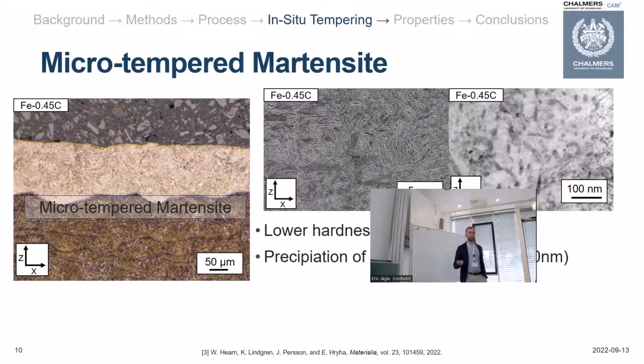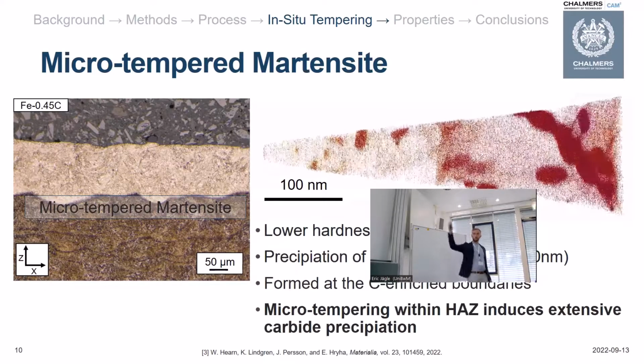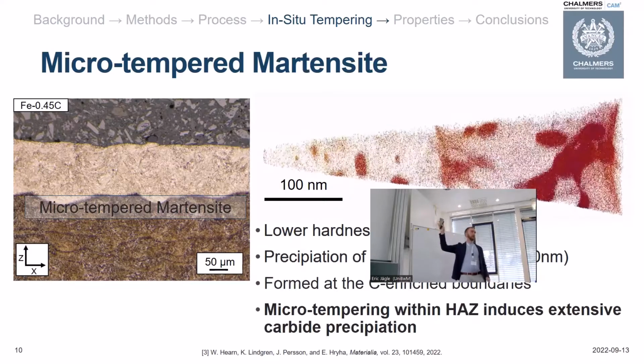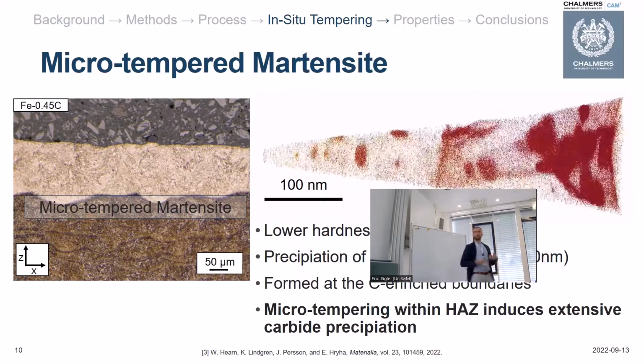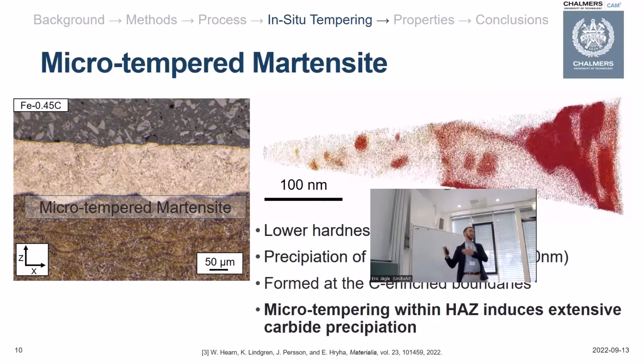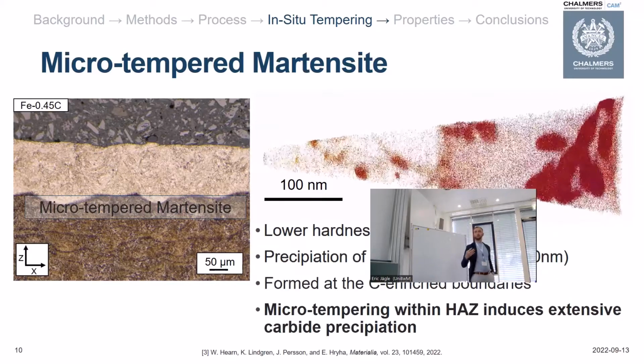You then look at both SEM and TEM, and now you have noticeable precipitation of carbides throughout your material, specifically cementite carbides that are very small, about 30 to 60 nanometers. And again, when we start looking at APT, we see these cementite carbides located, and they have precipitated at the previously carbon-enriched boundaries of your material. So essentially, the micro-tempering that happens within your heat-affected zone induces extensive carbide precipitation that helps you reduce the hardness of your material and its susceptibility to cracking.